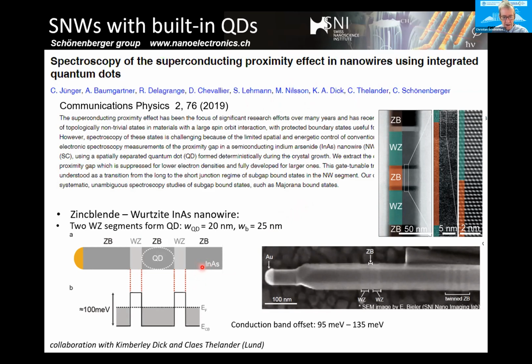So the nanowires are basically zinc blende nanowires. So they're typically a bit large in diameter, maybe 100 nanometer or so. And then the Lund people are able to change the crystal phase during growth. So they can switch from zinc blende to wurtzite. The wurtzite has a bigger band gap than zinc blende and gives about a potential step in the conduction band of around 100 millielectron volt. So this is a smaller barrier, means the wurtzite barrier has to be a bit longer. So typically growth of this length is about 20 nanometer.